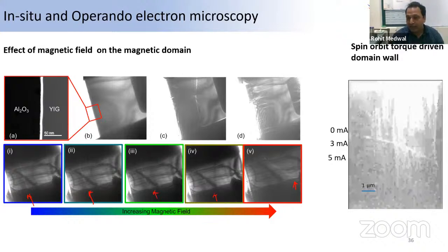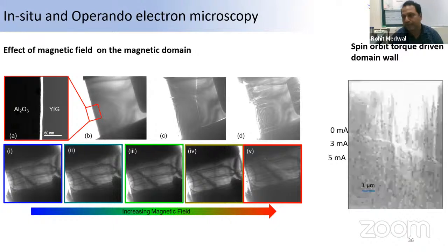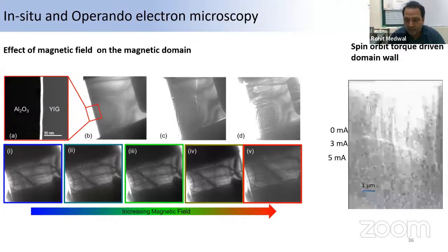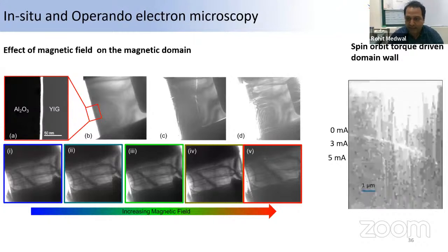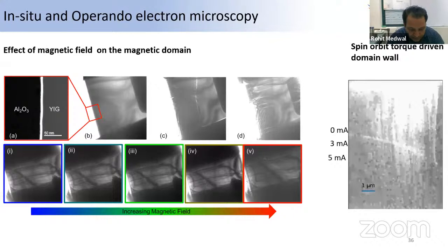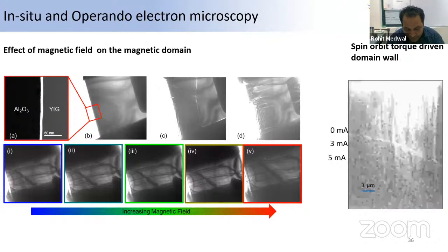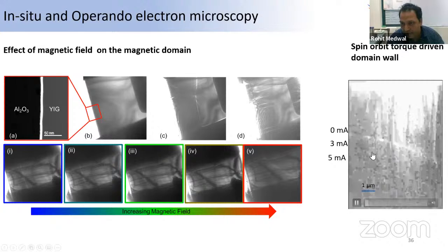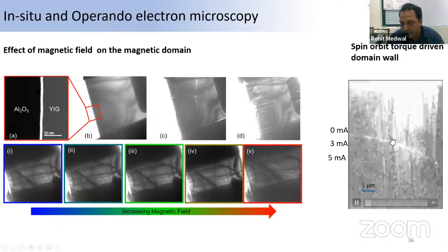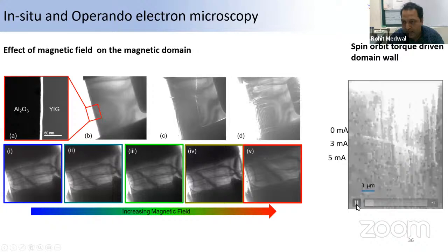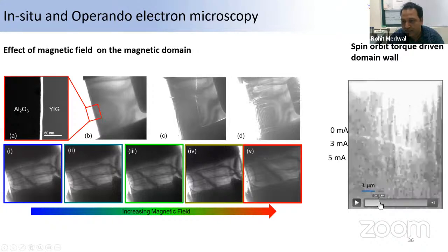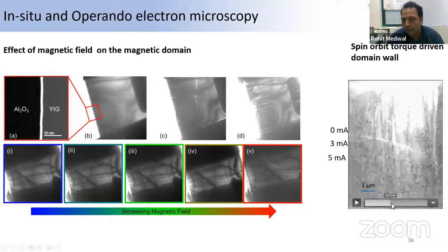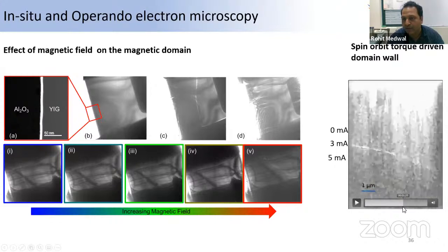And we did this in situ experiment with current. So we apply the current to convert it to spin current. You can see here, maybe I can show clearly in this one. This is the domain wall. My domain wall is here. You can see that. And the moment we increase the current, we can see that the domain wall is moved with 3 milliampere to one state here.